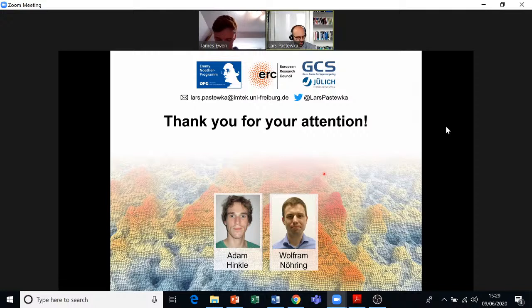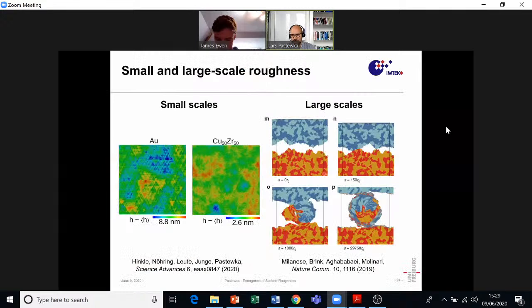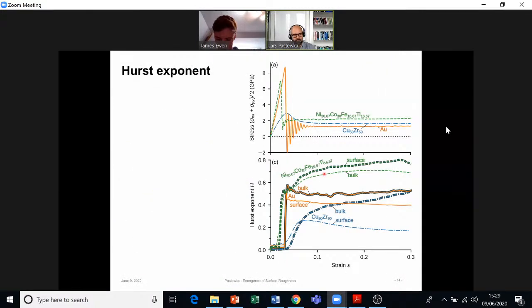First of all, hi Ramin, and so you were talking about the slide that shows the Hurst exponent. Is this one? Shear. I mean, the surface is traction free because we have a free surface. So we didn't really look in detail at the intrinsic stresses subsurface. This is what we find for the Hurst exponent in our systems. So it differs from these three systems. We don't really know why it differs in the way that you see here, but what we can say is that it seems to be relatively invariant with strain.